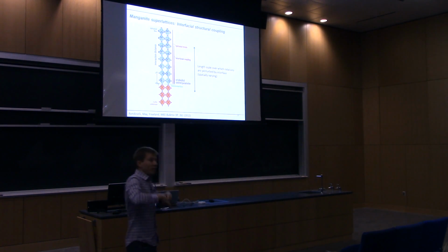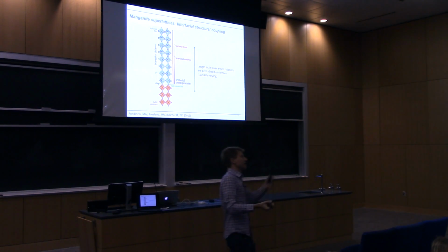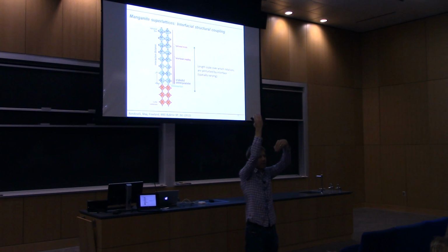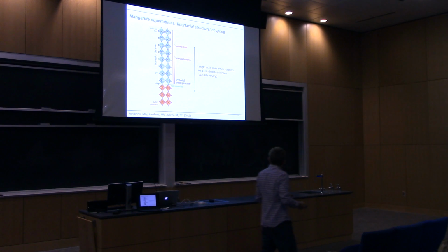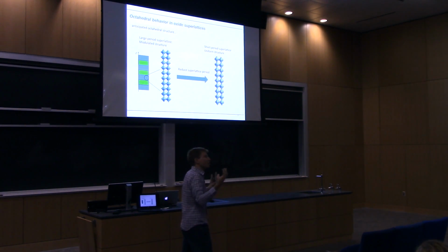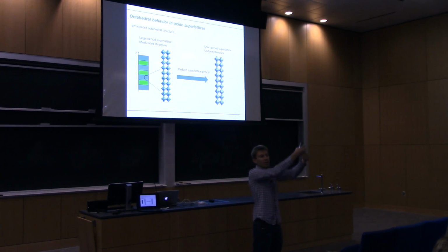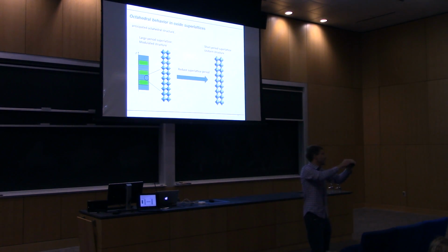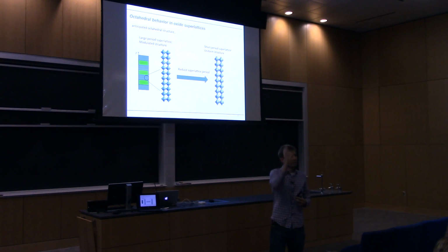As I mentioned, we can make these heterostructures and grow these materials layer by layer. So we can make superlattices where we have A, B, A, B, A, B, A, B, and we can control the number of layers within each of those blocks. Say we make a large period superlattice, with a lot of A, a lot of B, a lot of A, a lot of B. Or to put it another way, the distance between these interfaces is larger than this length scale for octahedral coupling. Then what we would have is very modulated octahedral distortions as we move along the growth axis.